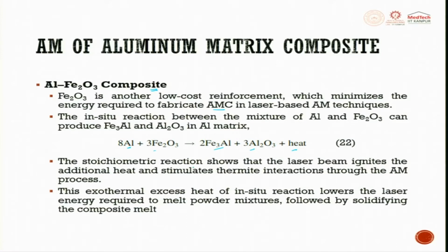The stoichiometric reaction shows that the laser beam ignites the additional heat and stimulates thermitic interaction through the AM process. The exothermal excess heat of in situ reaction lowers the laser energy required to melt the powder mixture, followed by solidifying the composite melt. So this is very important: the exothermal excess heat, and the stoichiometric reaction is maintained.